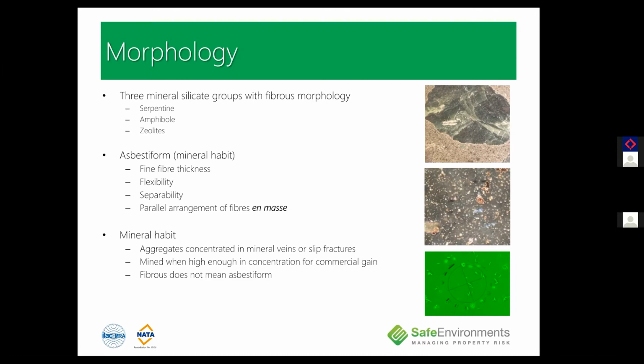If we look at the picture on the top right, we can see what appears to be a veiny rock. When we interrogate this and attempt to bring out and separate fibres, they simply cleave laterally and form smaller fragments. In this instance, it initially appears to be tremolite asbestos under trace analysis, in which we can also see these respirable fibres in phase contrast microscopy.